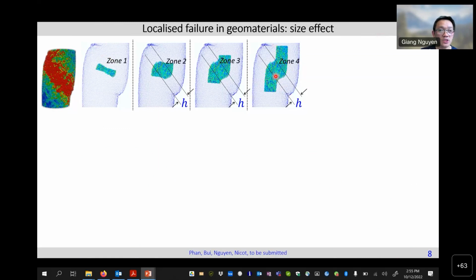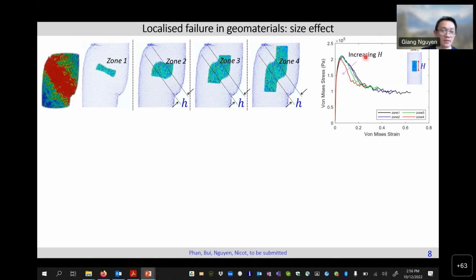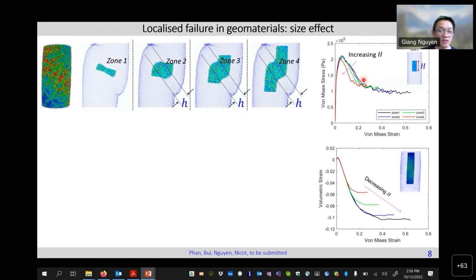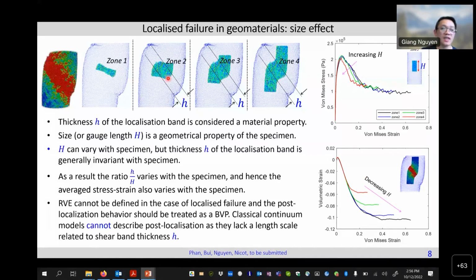We get the change in the stress strain responses. And if we are geotechnical engineers, we look at volumetric behavior. We see the response is changing with changing gauge length in this case, in loose sand, because in all 3 cases, the thickness of the band remains the same. So the only thing changing is our gauge length. Our gauge length is not a material property. It's our input. We want to measure strength over that gauge length, but the specimen is always localizing its deformation over the length h here.